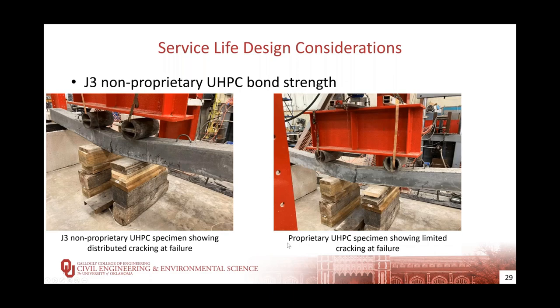The beam splice tests consisted of two number five bars with a two bar diameter lap splice at midspan to create a more realistic bond stress condition. The beams were then loaded to failure using a third point load arrangement. In general, the non-proprietary UHPC specimens exhibited distributed cracking along the length of the beams, while the proprietary UHPC specimens exhibited fewer discrete cracks.